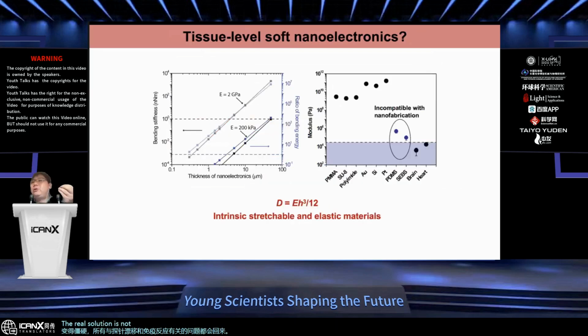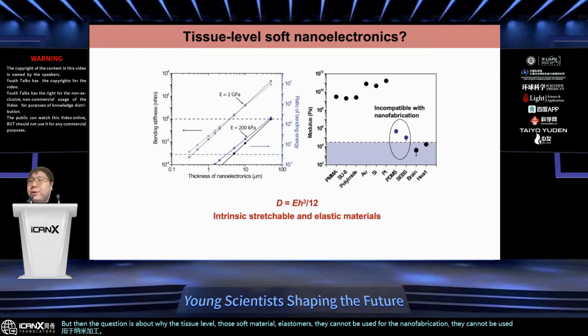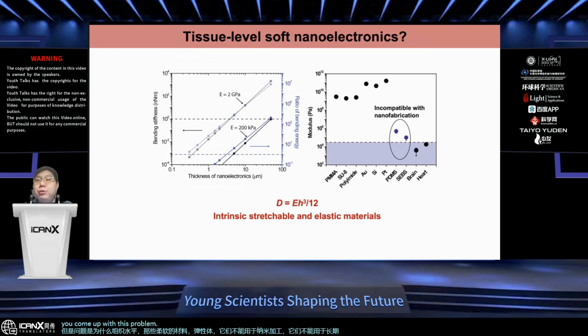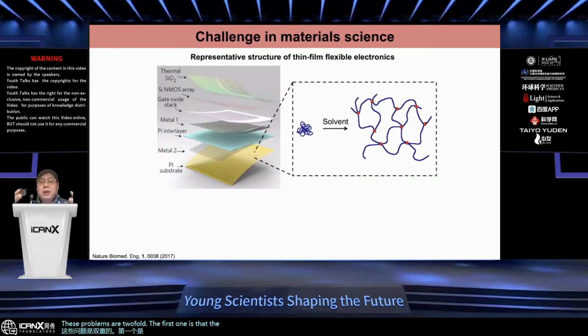The real solution is not just to reduce the thickness of the device, but also to reduce the intrinsic Young's modulus of the material, especially the dielectric material used for this flexible brain probe. Now we really need to introduce tissue-level soft materials for nanofabrication. But then the question is why those soft materials, elastomers, cannot be used for nanofabrication and for long-term stable brain-computer interfaces. It turns out these problems are twofold. The first is why the material is soft: academically speaking, its glass transition temperature is lower than room temperature. So you can consider them as cross-linked liquids at room temperature, or they have a microporous structure at room temperature.